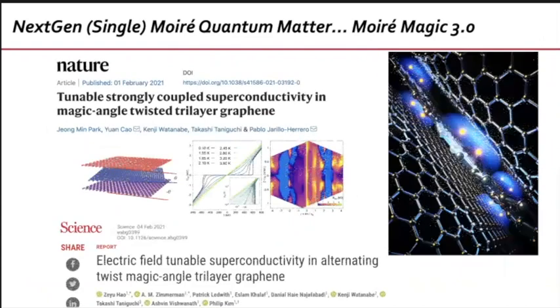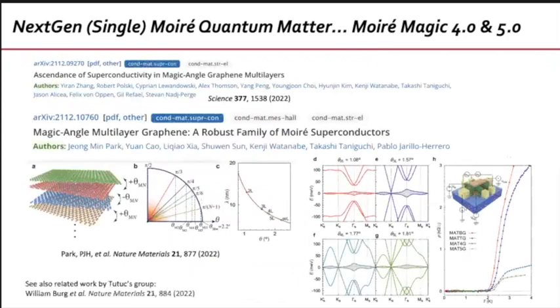So what my group and the group of Philip Kim discovered, now two years ago, is what we call Moiré Magic 3.0. If you put three layers of alternating twisted graphene at the magic angle for three layers, which is different, roughly 1.56 degrees, then you get strongly coupled superconductivity. In both groups, we obtained very similar results. You can do this with four and five layers, and the group of Stevan Nadj-Perge, my group, and the group of Emanuel Tutuc all discovered that indeed, with four and five layers, you also get a robust superconductor.